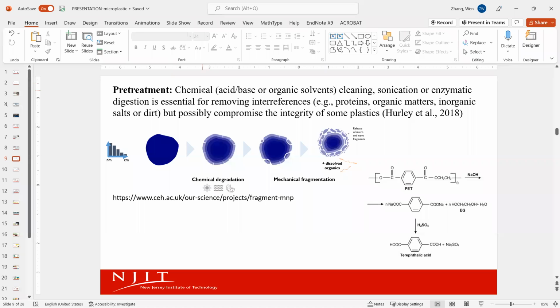So the pre-treatment is a step where we usually use chemical cleansing to cleanse up the plastic particle matrix using organic solvents like ethanol, methanol, or acid base to dissolve the salt or any dirts, inorganic matters, and some organic matters, so that we can largely prevent the interferences from those coexisting pollutants. But the problem is, as you can see already put down here, some of the plastics are vulnerable or fragile. They may undergo a mechanical or chemical degradation because, for example, you use the solvents and cleaning plus a sonication. And sonication is known to produce cavitation-based radicals, and also such high-frequency mechanical vibration would somehow decompose. You see here, it's really just a mechanical decomposition. And also the acid base, usually the plastics are not really able to tolerate high alkalinity.